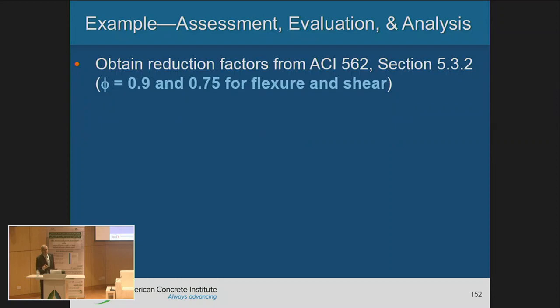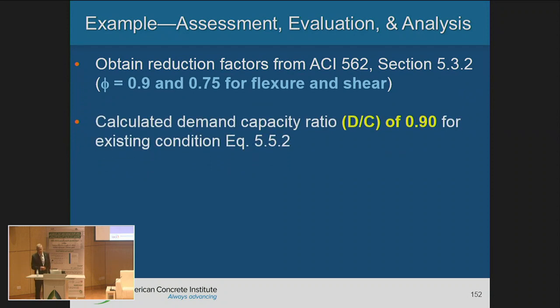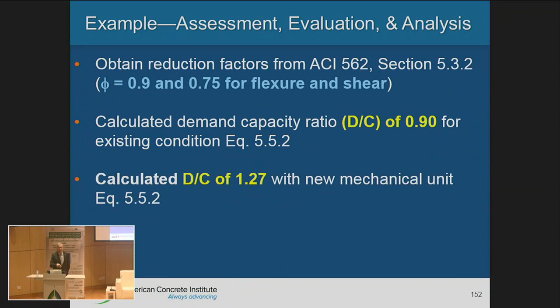Because he hasn't really determined the material properties, although he checked the member sizes, we use the lower reduction factors, 0.9 and 0.75 for flexure and shear, respectively. If I do my demand capacity ratio based on the historical data, it's 0.9. It's less than 1. That means my structure is okay. It's safe, and it satisfies the original code requirements. But when I added the unit, it came out to 1.27, much higher. So that means I need to reinforce the structure, right?